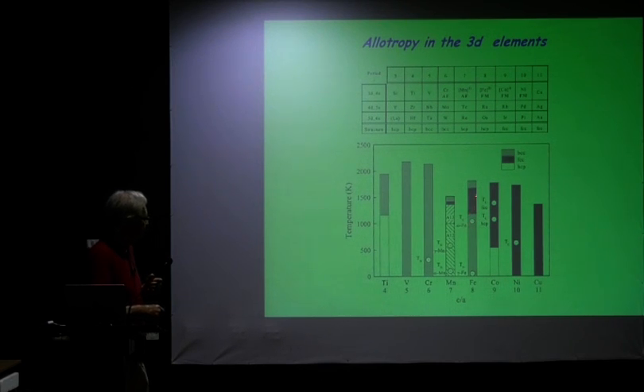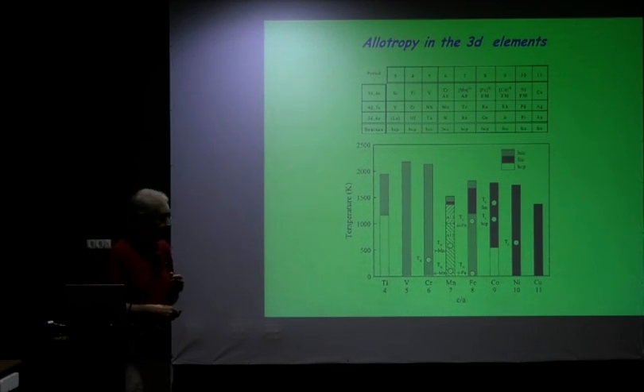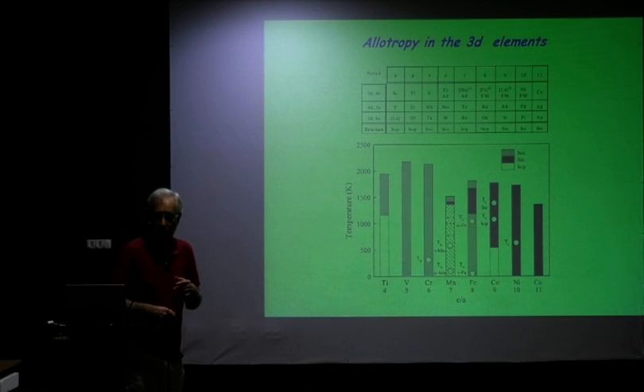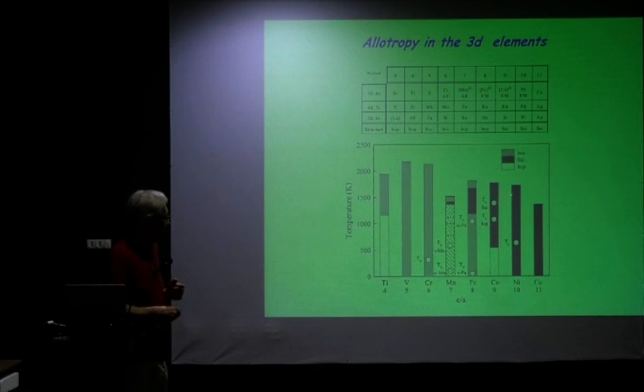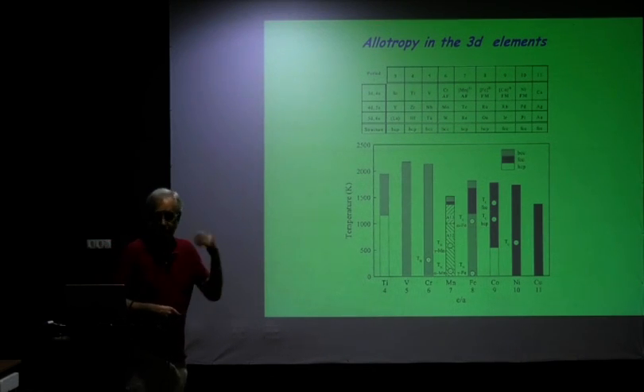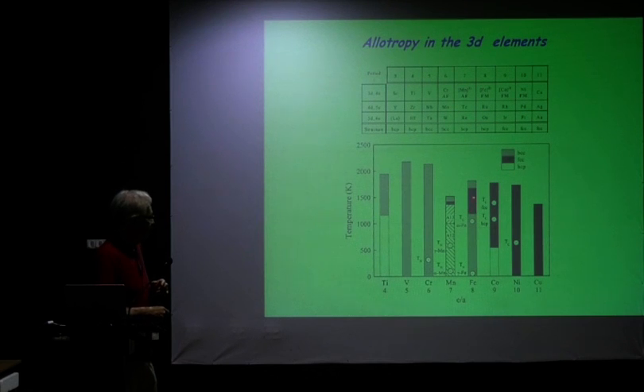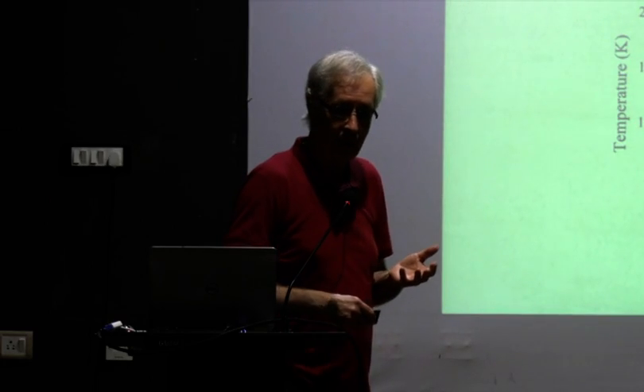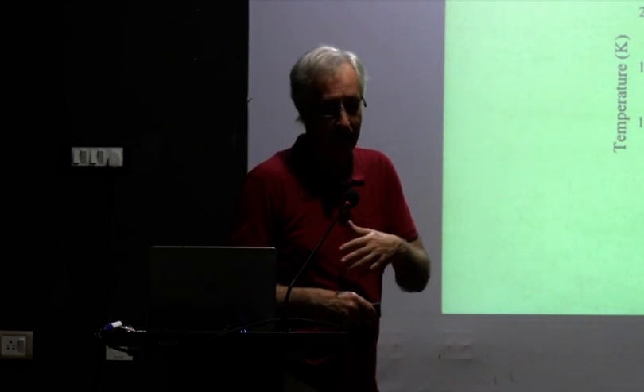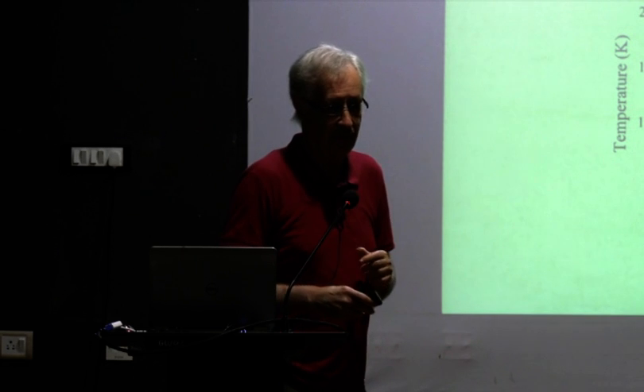And then we have FCC iron, a region where suddenly, when the magnetism is lost, the BCC state is no longer stable. It goes into a more densely packed structure. And FCC iron can be in an antiferromagnetic state with a Néel temperature somewhere around 70 Kelvin or so. That can be estimated. But it cannot only be antiferromagnetic, it can also be ferromagnetic, depending on the atomic volume. We'll go into that.